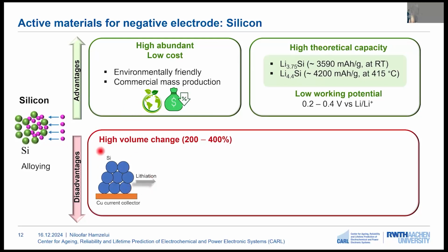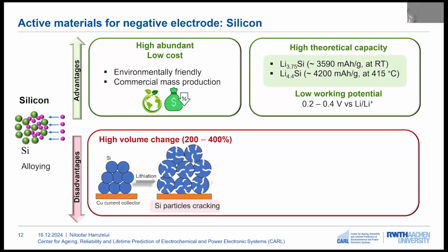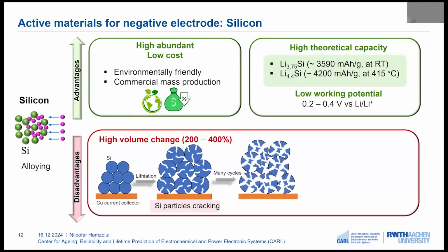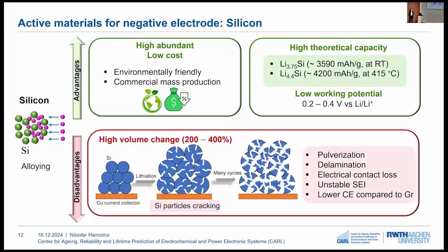So when we lithiate a silicon electrode, the silicon particles expand, and this can result in cracking in the silicon particles and in the electrode. And then after cycling the electrode for many cycles, and due to this constant volume change of silicon, we will have pulverization, delamination of the particles, loss of contact from the copper current collector, unstable solid electrolyte interface, and also it shows a lower coulombic efficiency compared to the graphite electrodes.